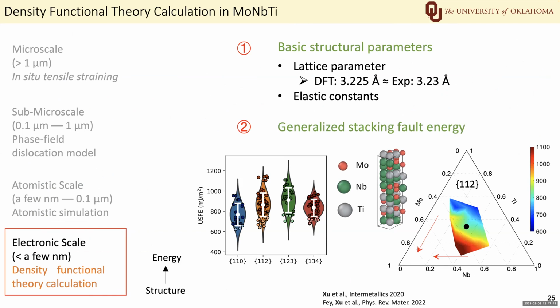Next, I calculate the generalized stacking fault energy, which is the local energy required to shift half of the crystal with respect to the other half. In the bulk material, the three chemical elements are equimolar, but locally they are not. So the local energy would depend on the local chemical composition. For example, if there are more molybdenum atoms or fewer niobium atoms, the stacking fault energy would be higher.